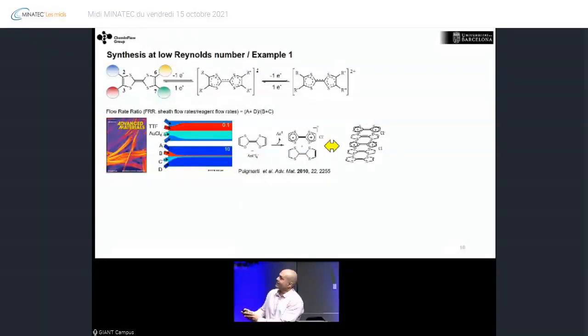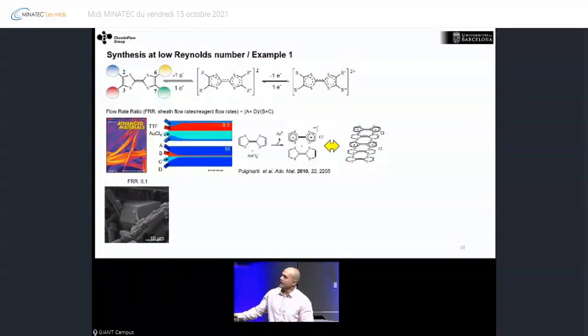The same molecule, but note that here we don't have any functionality. It's the bare molecule. We oxidize it with a gold salt, so the gold will reduce, and we expect to have this pi-pi stacking of the molecule. What we are changing now here is the flow rate ratio that is defined as the ratio of the seed flows, these blue flows here, A and D, divided by B and C, which are the reagents, the TTF and the gold salt.